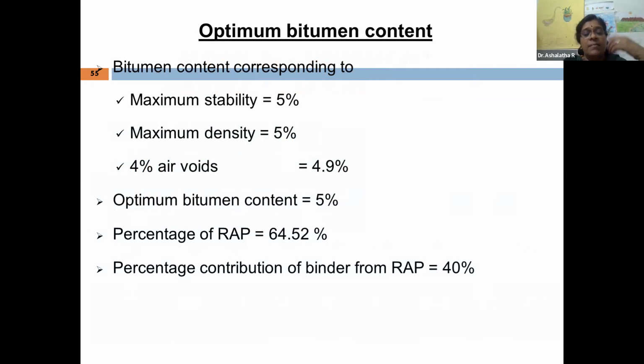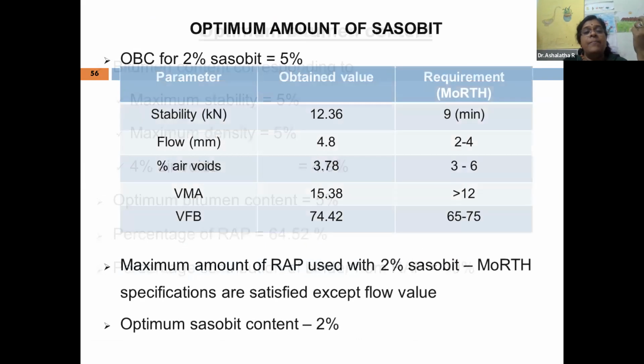I told you it's on the higher side, and the percentage contribution of binder from RAP was 40%. So we compared those values with the MoRTH specifications, and you could see that the MoRTH specifications were satisfied, except slightly the flow value, because we got it as 4.8, where the upper limit was 4. Otherwise, all of the values were satisfied.